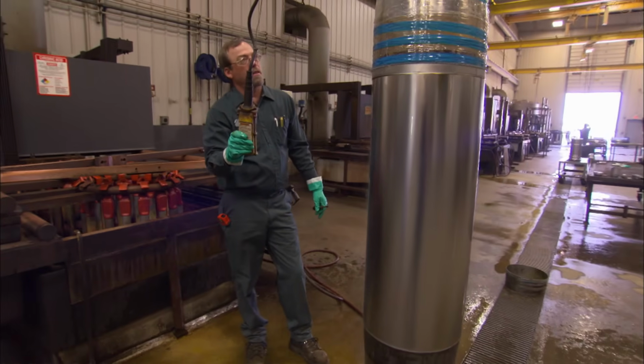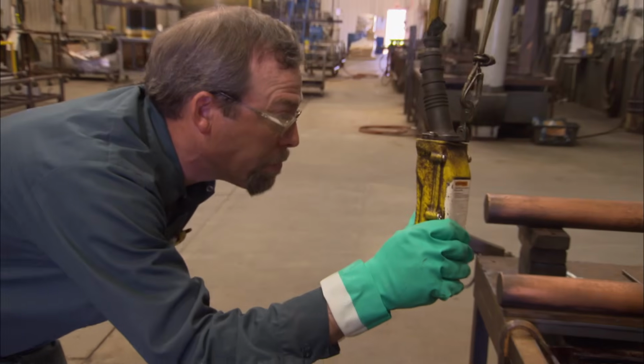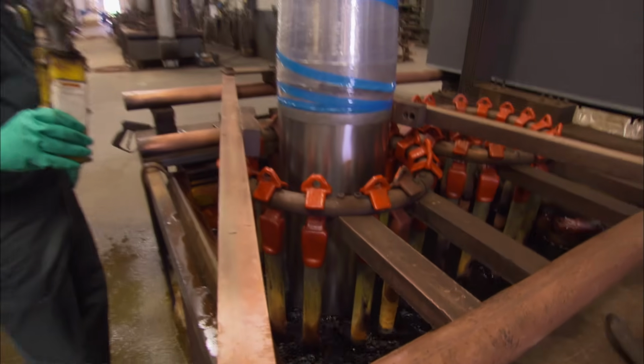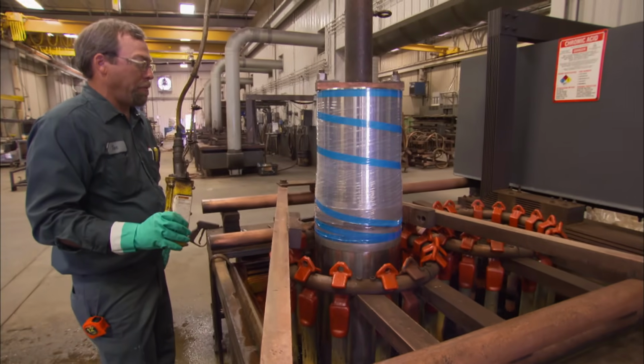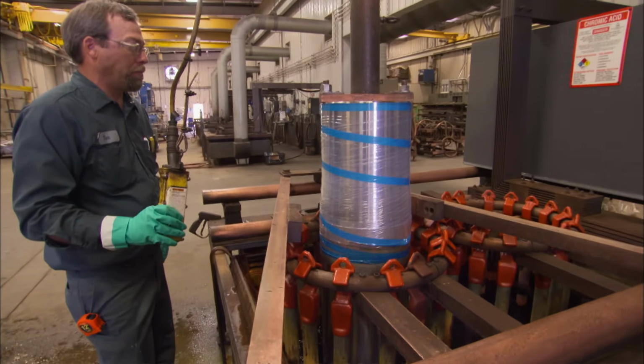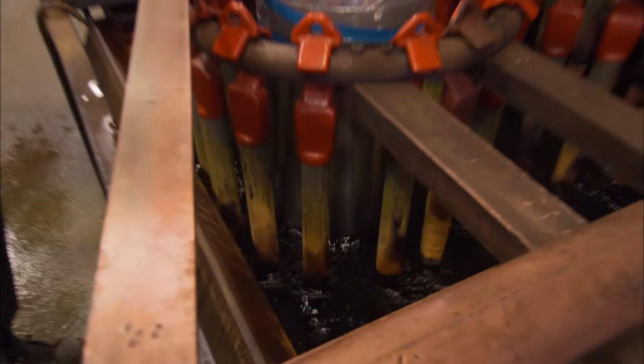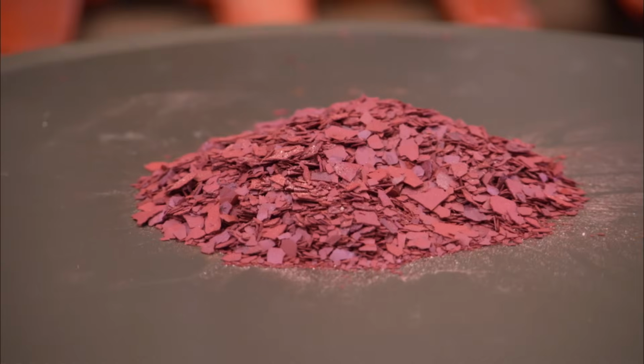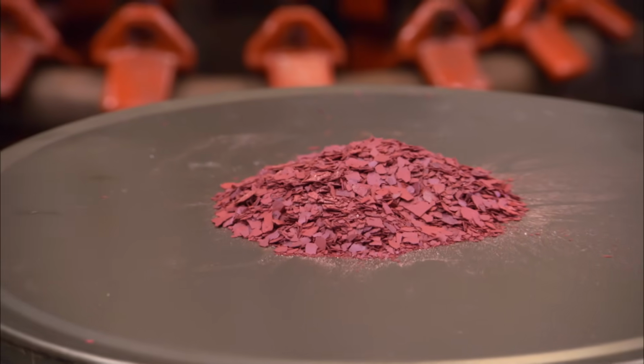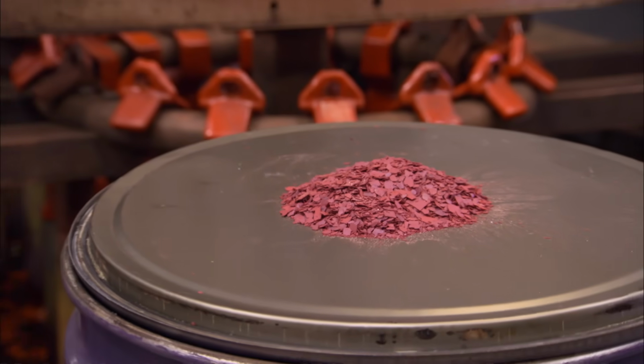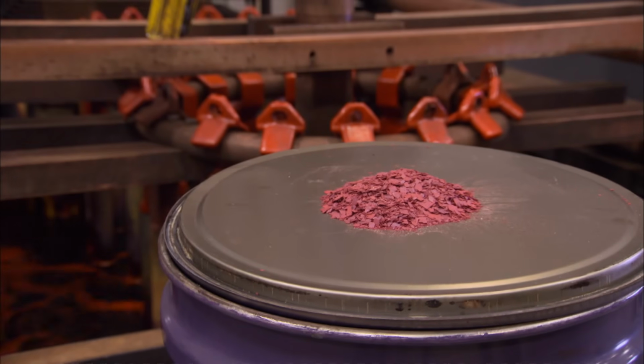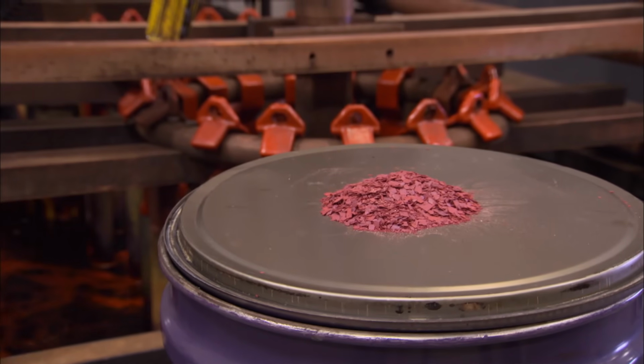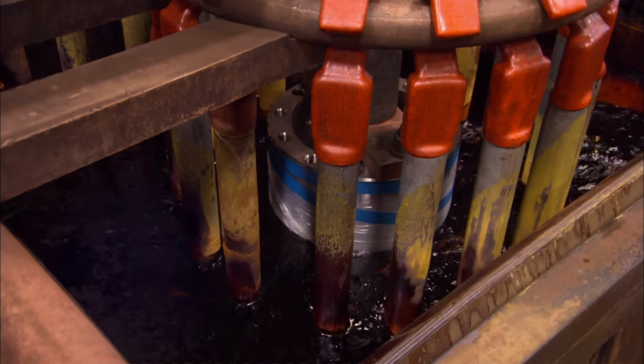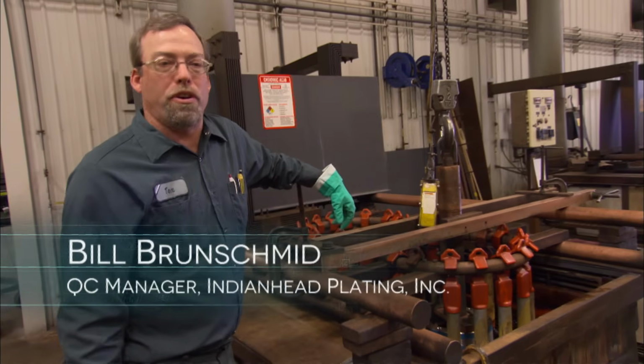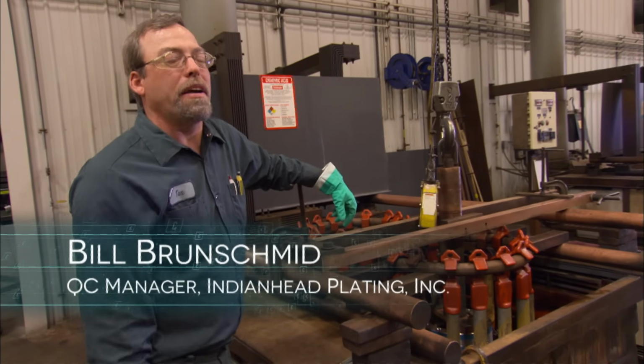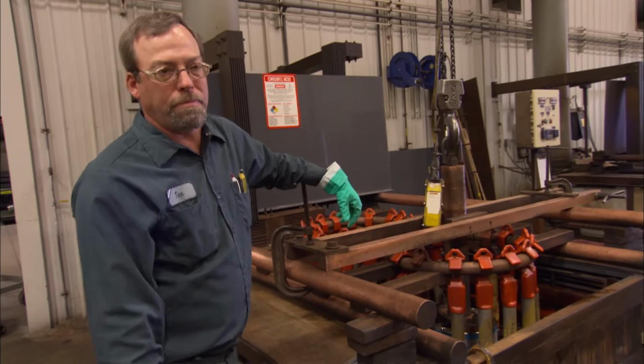Next, it's electroplating. To begin, a technician lowers each 1.5-ton unplated steel piston into a chemical bath of sulfuric acid and chromium flakes. These flakes are a combination of chromium and oxygen, known as chromic oxide. In this flake form, the chromic oxide has a reddish-brown color. The bath has to maintain about 138 degrees to be an accurate plating temperature.